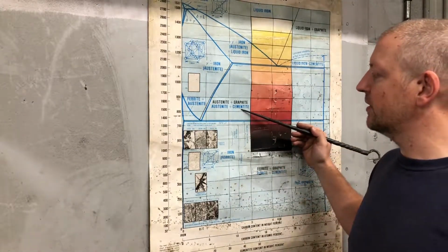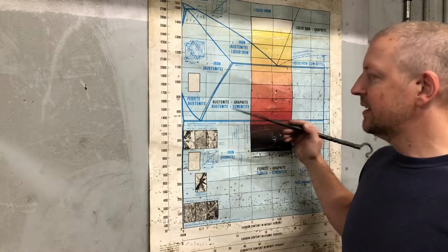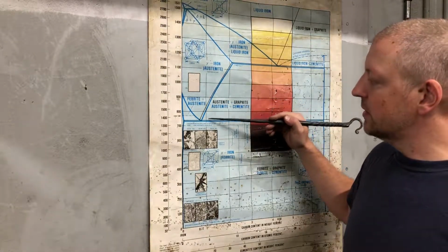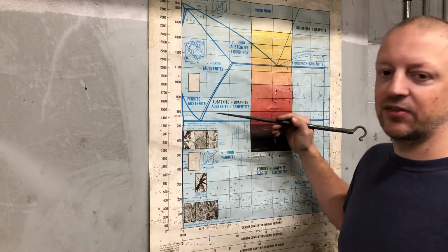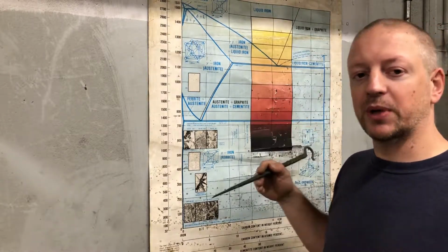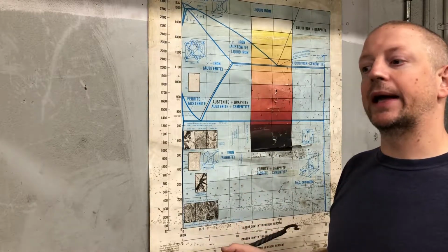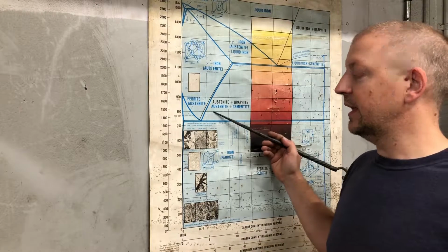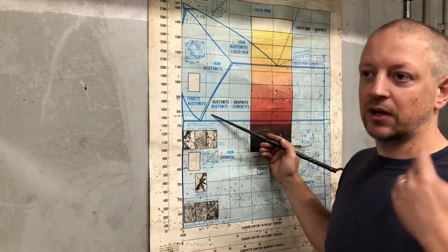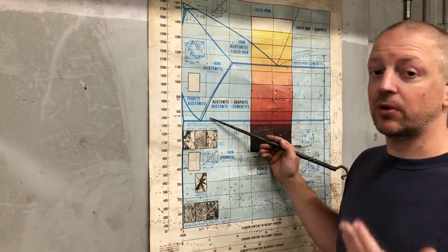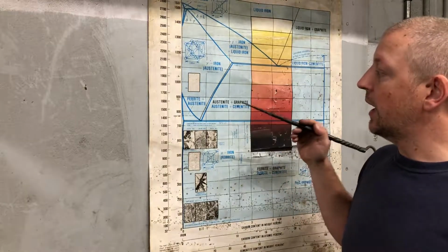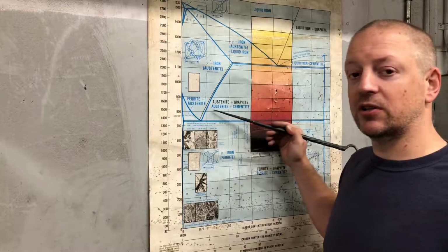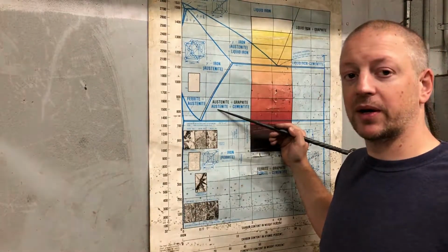So if you've got austenite and cementite, this means you don't have full austenite. However, you could very easily have enough carbon in solution to get full hardening. You could hit 62, 64, even 65 Rockwell without putting all the carbon in solution, leaving yourself some carbides.